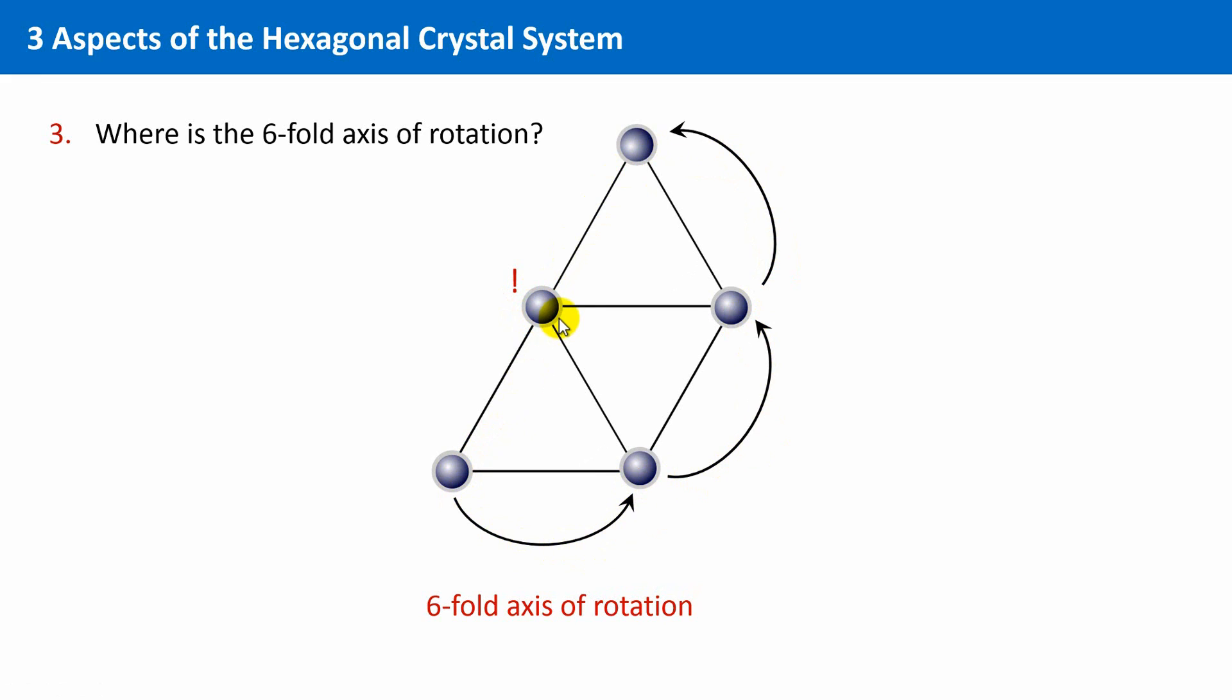You might think that this is just a trick, because this point here belongs already to the neighboring cell. But the crystal actually does not care. It does not matter because of the translational principle, because we are dealing with an endless and infinite lattice.